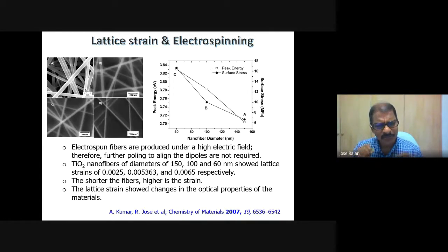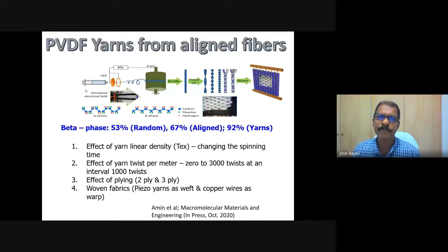And we get the fiber bundle. That fiber bundle is twisted to get yarns, and then those yarns were plied to get stronger yarns. And finally, these yarns were woven to get a cloth. There is a comparison given here. In the case of random fibers, where the fibers are randomly oriented in your fiber cloth, there is still a significant fraction, over 50%, of the beta phase present. It's about 53% in the case of random. But when it is further aligned by means of electric fields, it gets better poling and about 67% fraction is beta phase.